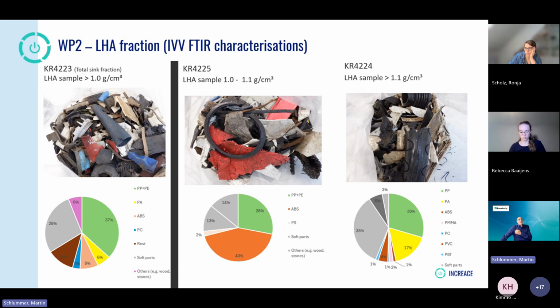Just to give you an example of how these fractions may look: here from the total sink fraction in the beginning, then the separated sink fractions 1.0 to 1.1, and the larger than 1.1 density fraction. You always see a somewhat different composition of the materials, with the majority being polyethylene and polypropylene. Here it also contains some ABS and PS in addition. And you see that even from the large one, we can make use of polypropylene, polyamides, ABS, polycarbonate, whatever you look into.